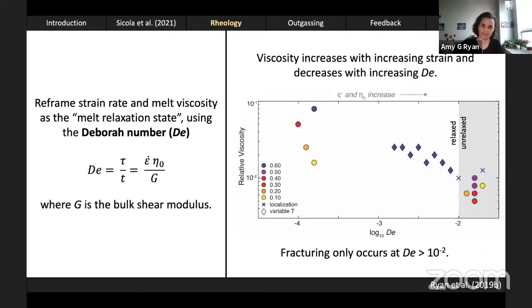So what I can do then is I can put all of my measured viscosities onto a single plot and interrogate them this way. And what I observed, using the mechanical data and calculating viscosity, is that viscosity increases with strain, but decreases with increasing Deborah number. Note that strain rate and melt viscosity increase going this direction. A Deborah number of 10 to the minus 2 has previously been defined as delineating a regime where materials are relaxed or unrelaxed. It's previously been described even as a viscous brittle transition. And so I've colored it in gray here.